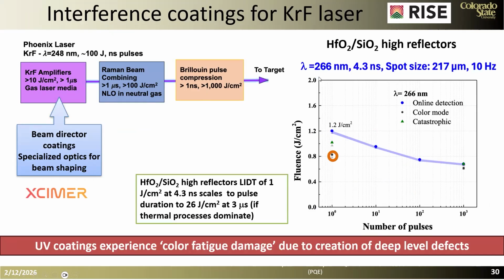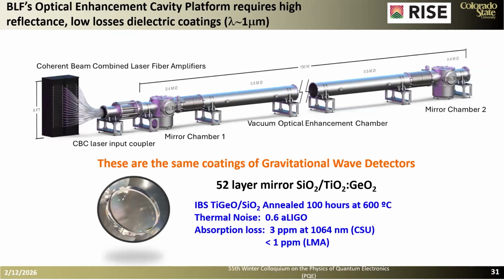We have been looking at hafnia silica coatings, and we have done some studies to understand the laser damage behavior and the fatigue behavior that the coatings show whenever we have multiple pulses. This simulates high repetition rate. In support of the Blue Laser Fusion concept, we are using the design of the coatings that we have for LIGO. Now what we are trying to do is modify the materials to achieve a higher laser damage threshold.